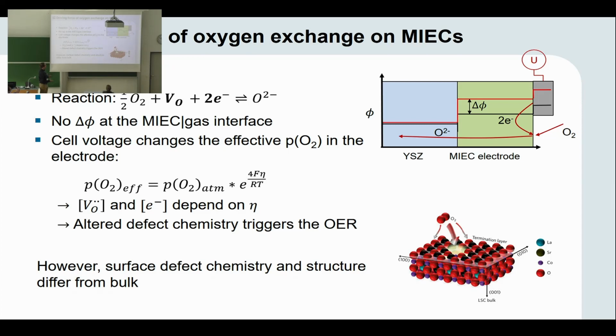However, due to the electrochemical nature of the reaction, when we apply a cell voltage, also the effective oxygen partial pressure that defines the defect chemistry of the mixed conductor changes due to the applied voltage according to Nernst's equation, which is shown here. And as I have shown previously, the defect chemistry, so the concentration of oxygen vacancies and electronic carriers, depends on the oxygen partial pressure. So we alter the defect chemistry of the material, and thereby we trigger either the oxygen incorporation, oxygen release, as well as hydrogen oxidation or water splitting reaction, depending on the gas phase.